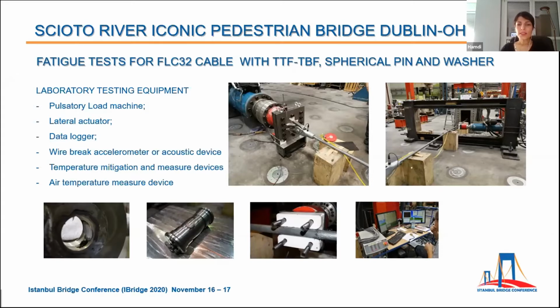In the photos, you can see the setup of the test with a pulsatory axial load machine, lateral actuator, data logger, wire break accelerometer, and measurement devices. For this test, Redaelli have designed and provided the connection plates and saddle for the lateral actuator together with the procedure to perform the tests. In this test, also the spherical pins were included. And as it is visible in the picture, the test was successful, and after the test, the element was free of any sign of damage.